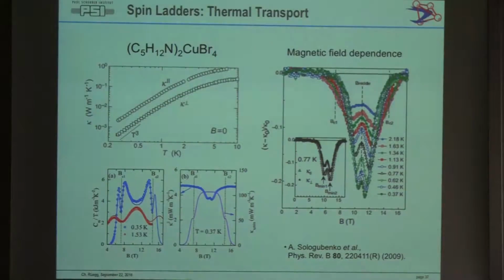Experimentally, it's high. The blue curve, that's experimental points. So basically, this has no offset or so. This is of course a pure measurement which has a phonon contribution as well. That's why it goes up. But in principle, there's a finite contribution here because of course it's not only from the spinons. But this is ladder material.